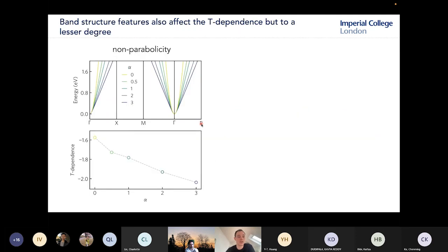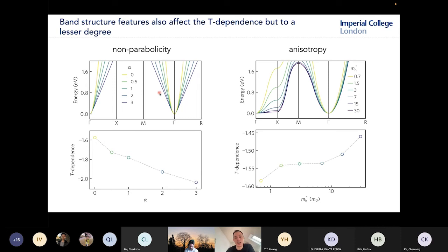We did look at other band structure effects, such as non-parabolicity. So here I'm looking at non-linearities of the band structure away from the band edge. We also looked at anisotropy. These have some effect, but much smaller compared to the phonon frequencies.